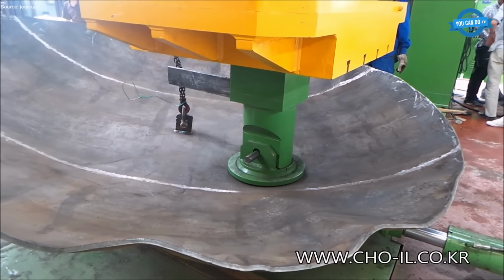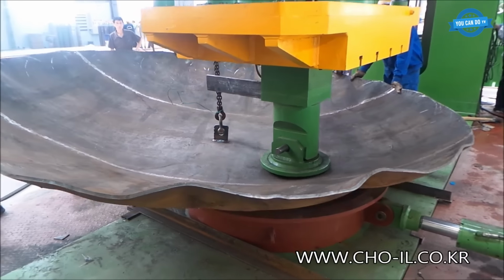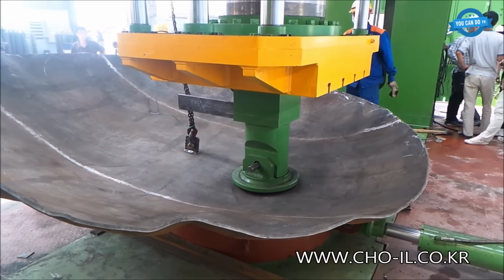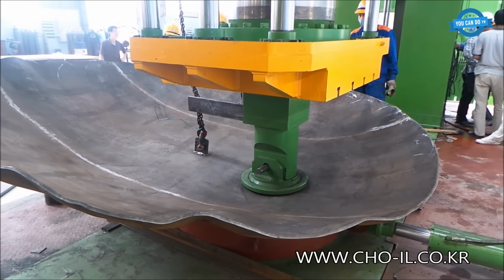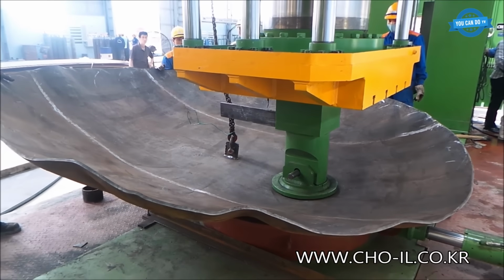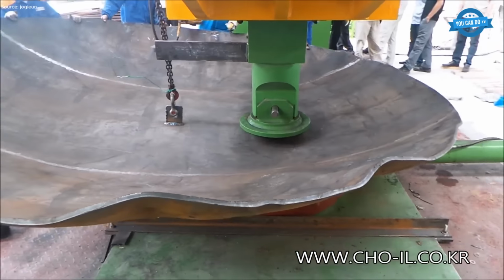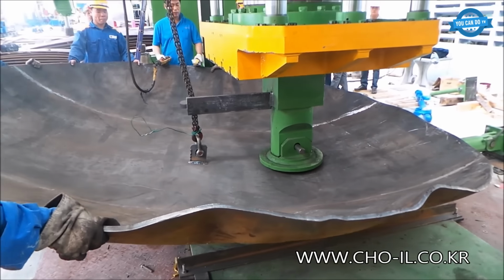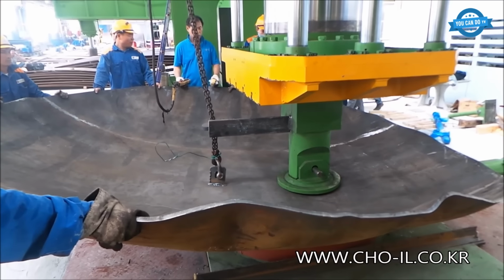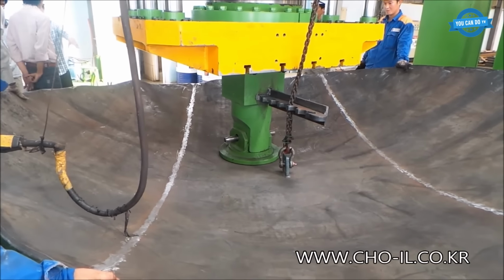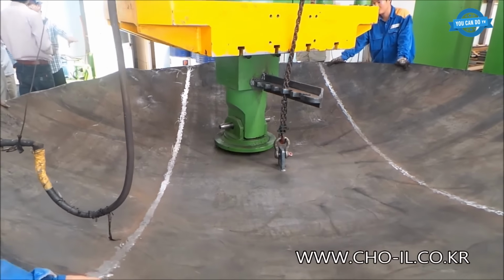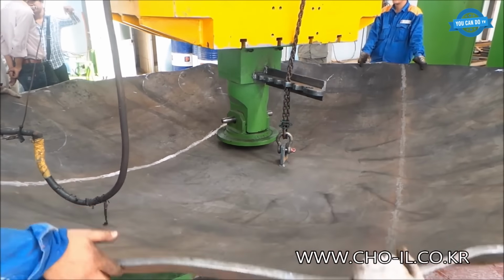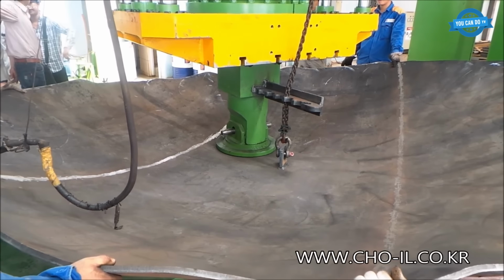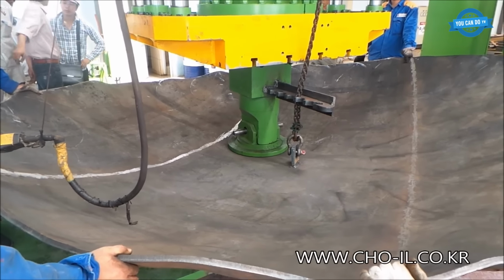The first major forming stage takes place on the 800-ton hydraulic press, a massive machine designed to apply enormous vertical force. The steel segment is positioned between specially designed forming dies that gradually shape the plate into a curved profile. As the press descends, hydraulic cylinders generate tremendous pressure, forcing the steel to deform plastically without cracking or weakening its internal structure. This step establishes the primary curvature that will later define the circular flange.